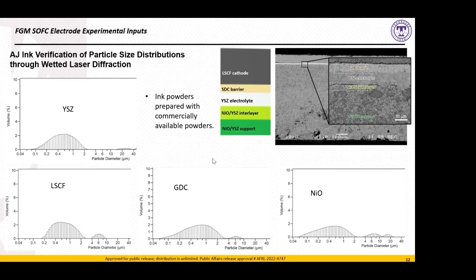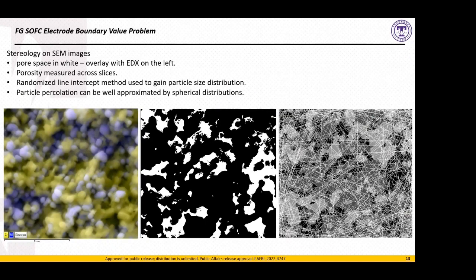So here we have the particle size distributions for these various powders, and we can see here, noticing that the x-axis is a logarithmic scale, that these can all be assumed to be log normal distributions. Some of them show some bimodality, but overall they are log normal in their distribution. As well, once we print a cell, then we can image it using scanning electron microscopy, and then process those images. What you see here on the left-hand side is an overlay of an SEM image and an EDX image, energy dispersive spectroscopy, which looks for certain atomic spectra. So here we have an overlay showing us exactly where the YSZ is in yellow and where the nickel is in the kind of bluish purple.